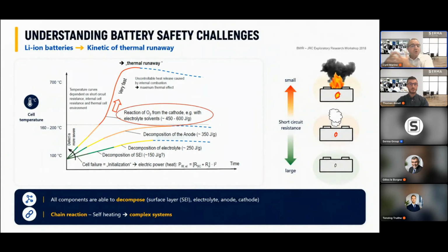And this heat will go to decomposition of electrolyte that will also create heat. So you see my point is that more and more you will increase the temperature of your system without putting more temperature in your system itself. So it means that this is a step-by-step configuration. This is why you can stop the reaction at some point by putting cold inside it. But of course, sometimes you cannot avoid the last part, which is the reaction that goes to thermal runaway.